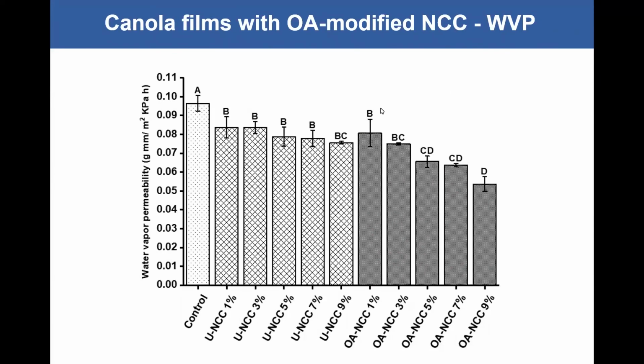What is most important is the water vapor permeability of these films, because especially with the oleic acid modification that we did, as you can see here, we managed to reduce the water vapor permeability significantly compared to the control films. So it looks like grafting a hydrophobic polymer is much more effective in terms of water vapor permeability in developing a packaging film compared to a modification like TEMPO mediated oxidation. So we are still working on the full characterization of this work, but this is what I basically want to